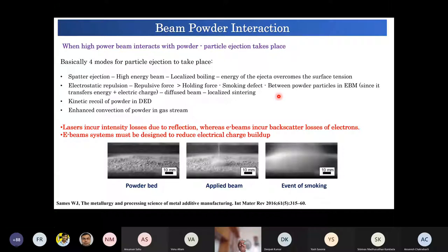And then that leads to a localized sintering, and there is a diffused beam, and that leads to localized sintering. Then there is a kinetic recoil of powders during the EB process, and then there is enhanced convection of powder in the gas stream. Many of these defects are related to e-beam processes, because if somebody has experience with e-beam, there is always powder that comes out of the process, right? So the powder bed is no more very smooth in that case.